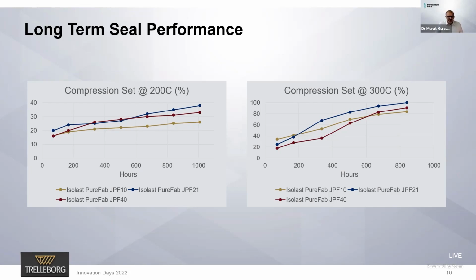As I said, elastomers are mainly used for sealing applications, and you can see the most important property of an elastomer when talking about sealing performance, which is compression set. So compression set is the amount of permanent deformation after some time at a constant temperature. So you can see two charts on the screen, 200 and 300 degrees Celsius,